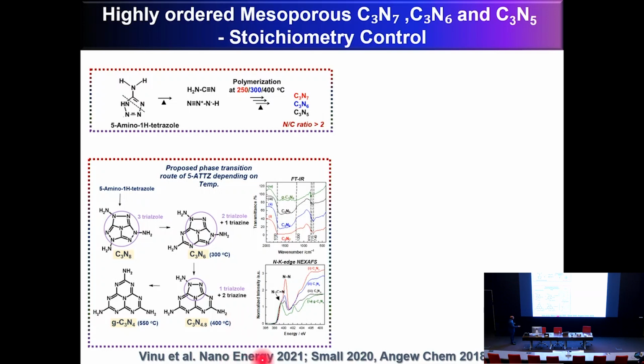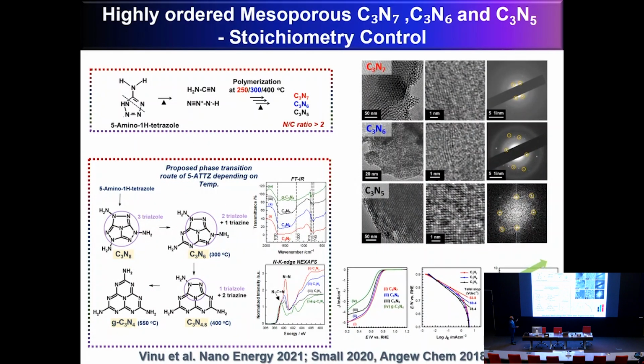Interestingly, when you look at this NEXAFS spectroscopy and FTIR, you see the intensity of the N-N bond increases, that is coming from the triazole molecule, right? So that's why you have different molecular structures. Now this is theoretically predicted, and it is not just a simple molecule, but a real material that you confirmed with transmission electron microscopy. And we use that one for the oxygen reduction reaction.